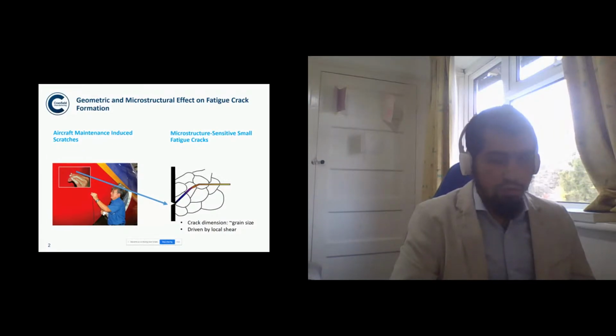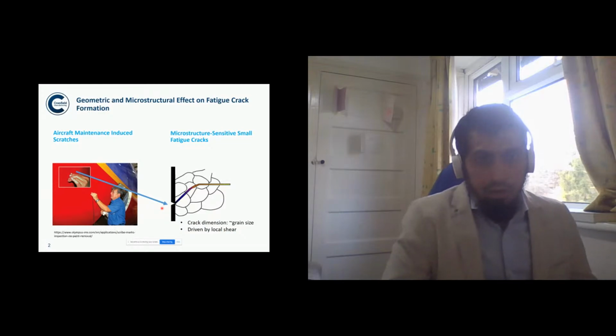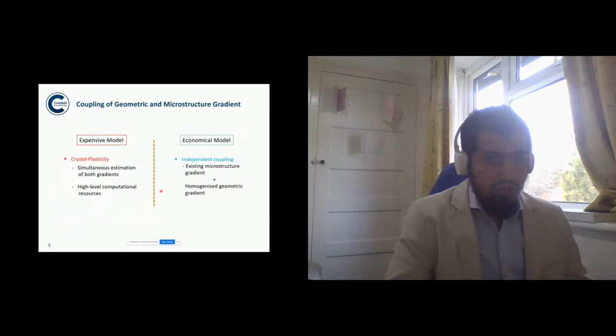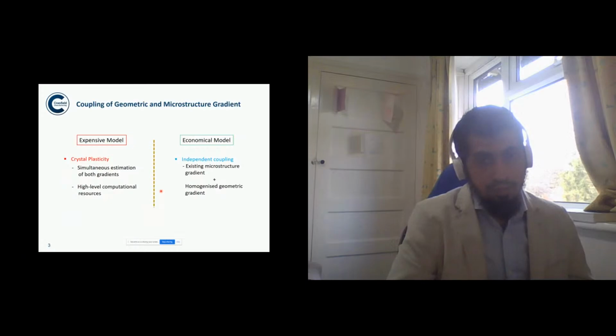In this fatigue problem, there are actually two gradients. One is the geometric gradient coming from the scratch, and the other is the microstructural gradient. For fatigue prognosis, we need to account for both of these gradients. The coupling of the geometric and microstructural gradients through the conventional crystal plasticity model is an expensive way of modeling, and it requires a high level of computational resources. Alternatively, we have proposed to quantify each of these gradients separately and couple them independently. This serves as an economical model, and it is less computationally intensive.